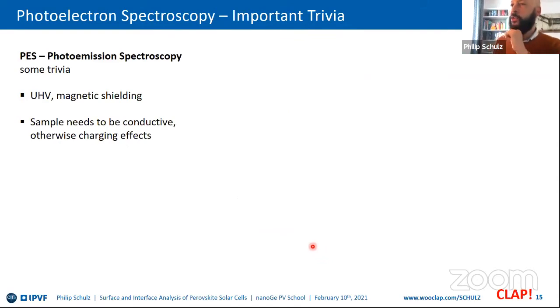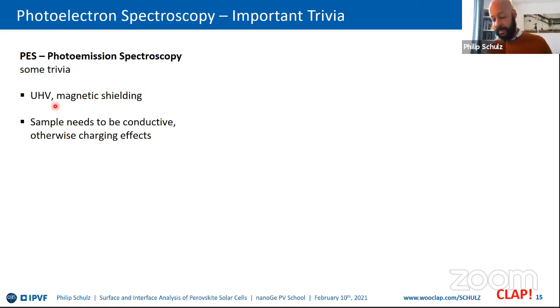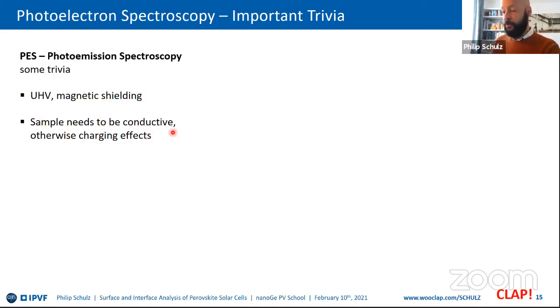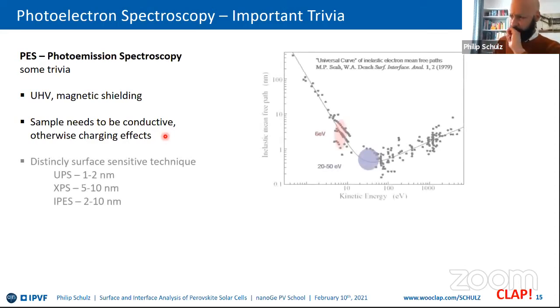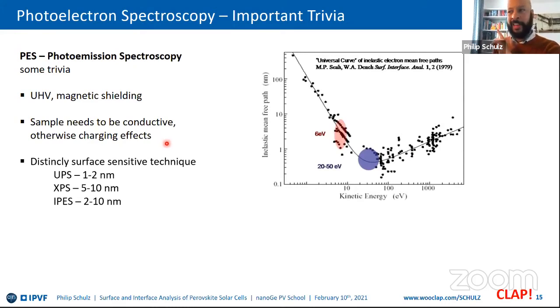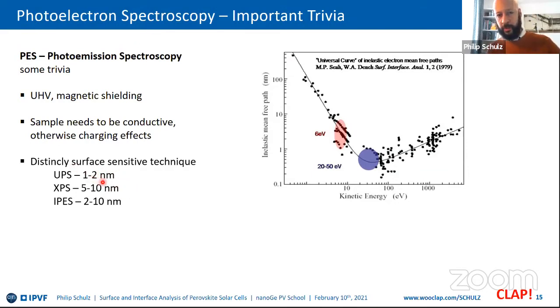Some important trivia for running these experiments: measurements must be done in ultra-high vacuum so electrons are not scattered by gas species; magnetic shielding is required to avoid deflecting electron trajectories; and the sample must be conductive, since emitting electrons otherwise causes charging that shifts the Fermi level to an arbitrary position. This technique is very surface-sensitive: in UPS the information depth is 1–2 nm; in XPS, 5–10 nm; in HAXPES, much more; in IPES, 2–10 nm. This is governed by electron scattering — the inelastic mean free path — not by photon attenuation.